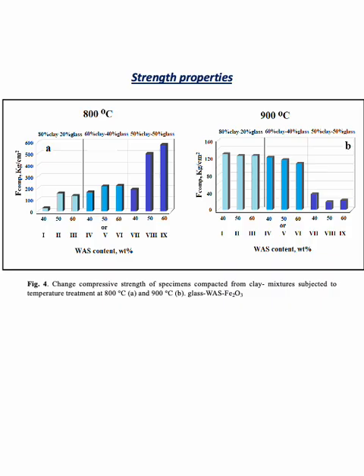Now, the strength properties of the specimens are shown in the next graphic. It is possible to observe that the compressive strength of the samples significantly depends on the composition of the mixtures and the temperature treatment of the specimens. In specimens treated at 800 degrees Celsius, we obtain specimens with ultra-strong force. But in comparison, the specimens treated at 900 degrees Celsius correspond to the standard values required for brick products, from 70 up to 150 kilograms force per square centimeter. The decrease in the compressive strength of the samples may be associated with the formation of a large number of compounds that are fragile compared to fayalite, such as wollastonite.